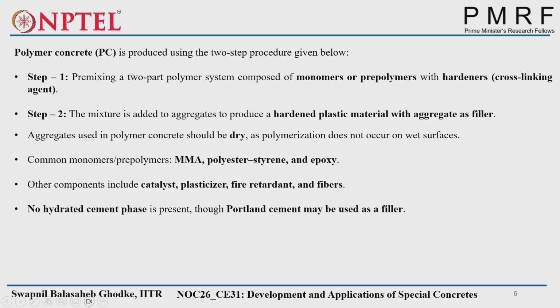Why is it saying no hydrated cement phase is present, though Portland cement may be used as a filler? Because we are not using water in the polymer concrete. So if there is no water, there is no chance to hydrate the cement or to get the CSH gel. So that's why whatever cement is available in the polymer concrete will only act as a filler.